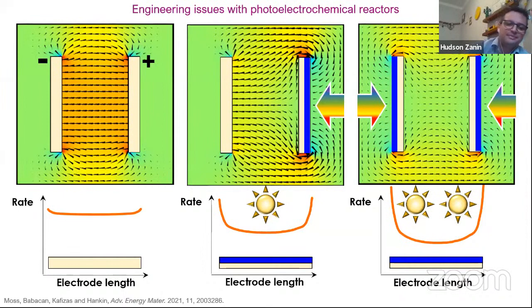to tackle it? Yep, so definitely if we're talking about either the middle case or the one on the right, such that, let's say in this scenario, you still have a very decent current density, as a result of which you evolve gaseous products. So if you have a chemically robust electrode, seeing bubbles is normally a very exciting experience, because, yay, gases, some respectable rate. But it quickly becomes a problem, because if these bubbles don't detach from the electrode surface and they keep growing, they of course scatter the incoming light. So they decrease the amount of light that actually reaches the photoabsorber. And the other problem is that if they stick to the electrode, they obscure part of the active surface area, right?